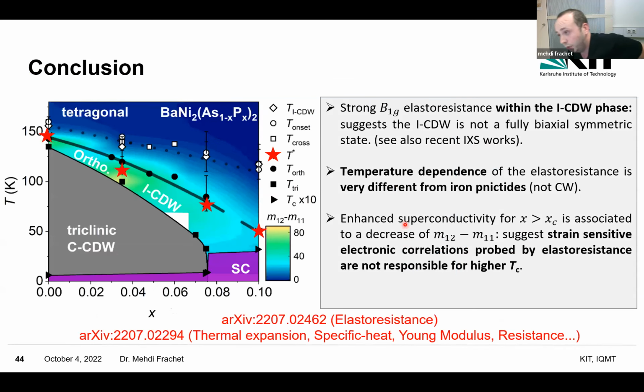This leads me to my conclusion with this color map phase diagram: temperature as a function of phosphorus substitution. What you can see is that we observe a strong B1G elastoresistance that onsets together with the incommensurate charge density wave phase, which suggests that this phase is not a fully biaxial symmetric state. That's also what was suggested by the recent inelastic X-ray scattering works. The temperature dependence of the elastoresistance is quite different from the iron pnictides in this phosphorus-doped barium nickel arsenide, and in particular, it's not Curie-Weiss.